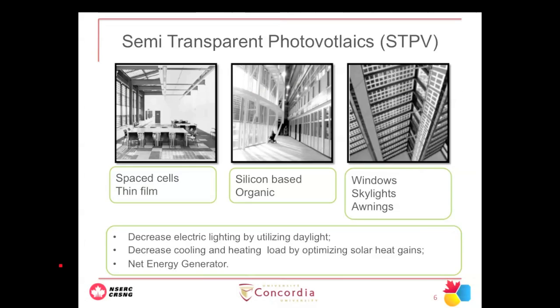So why semi-transparent PV? When talking about semi-transparent PV, I'm referring mainly to thin film transparent technologies, or spaced cells where light goes through the gaps. We're focusing on silicon-based and organic cells for skylight windows and awning applications. The reason is that for these huge glazed buildings we don't need all the sun inside — it would overheat the building. We can cut down solar radiation incident on the surface, allow some daylight to reduce lighting electricity, reduce cooling and heating loads, and even create a net-zero energy-generating facade.